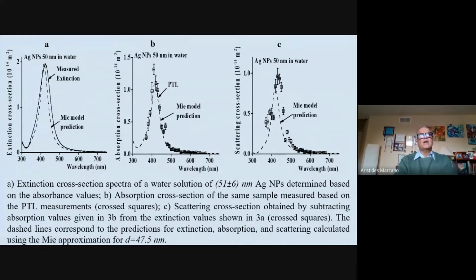That's a new way of characterizing nanoparticles. I think this is a very original way of characterizing nanoparticles, because usually you can measure the transmission and the absorbance. Maybe you can measure the scattering, which is a little bit more difficult, but you can do some scattering experiments, which are not simple. But you can do the thermal lensing spectroscopy and have a good complement and compare with the predictions of an excellent theory invented more than 100 years ago.